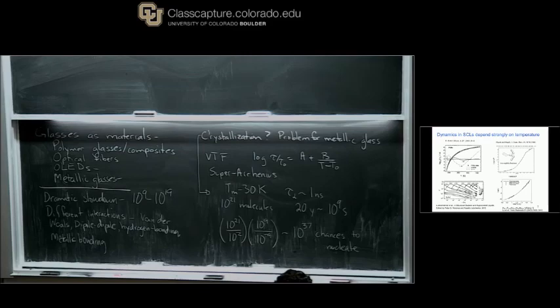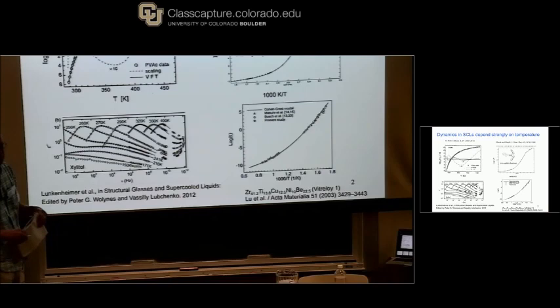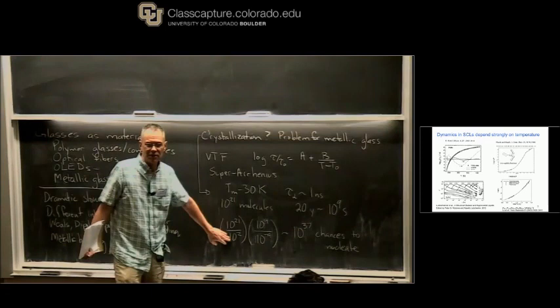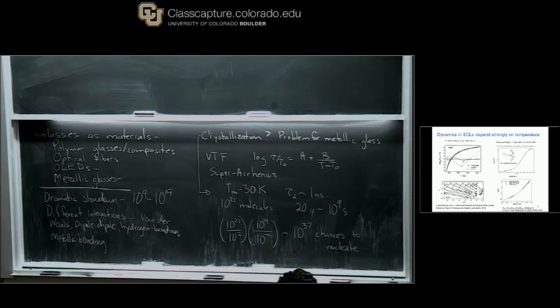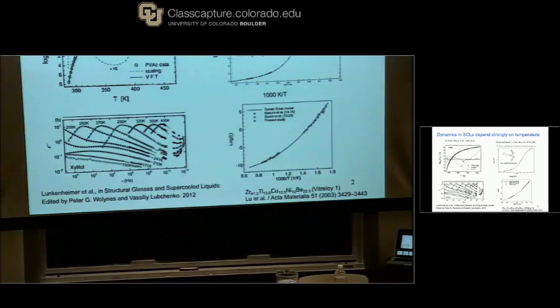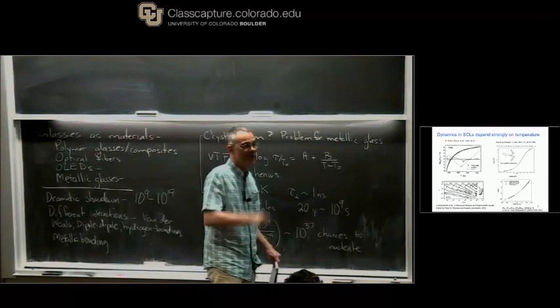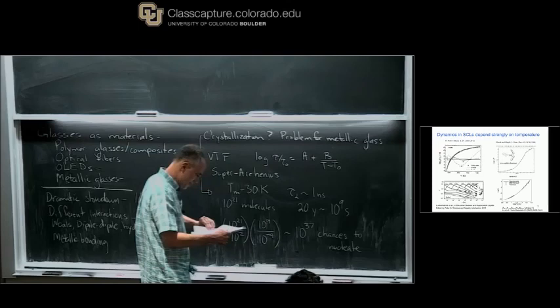The alpha relaxation time is a characteristic time for the system to relax — the structural relaxation time. We'll define this more carefully in the next plot. You have to make some estimate of what a critical nucleus size is — maybe it's 10, maybe it's 1000, but it's not really going to change the calculation much. Once it nucleates, the crystals would grow probably a centimeter per second at this temperature. So once it nucleates, you better be watching or you're going to miss it.